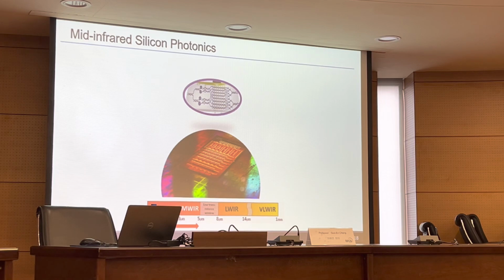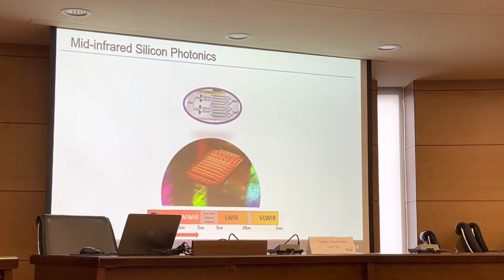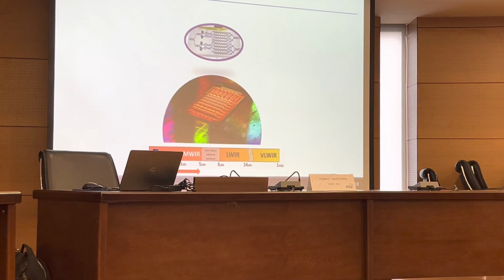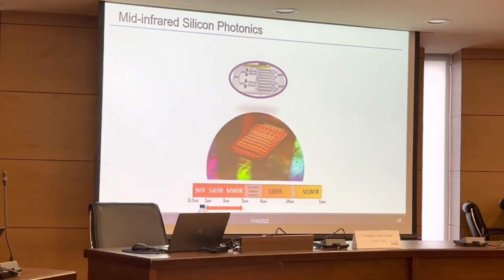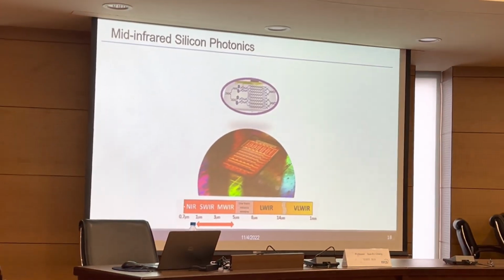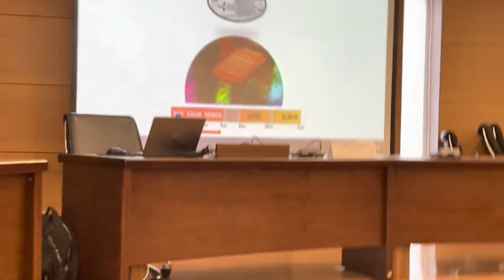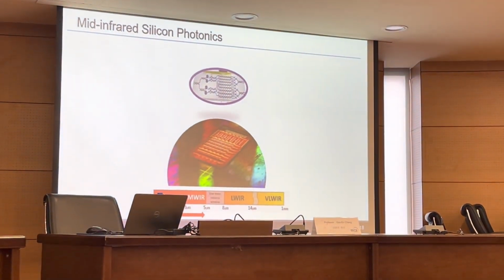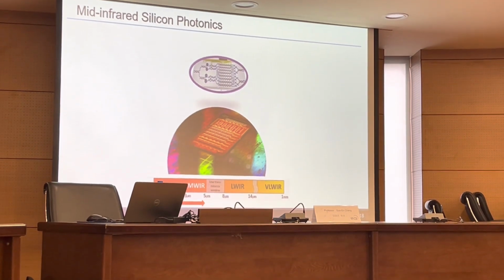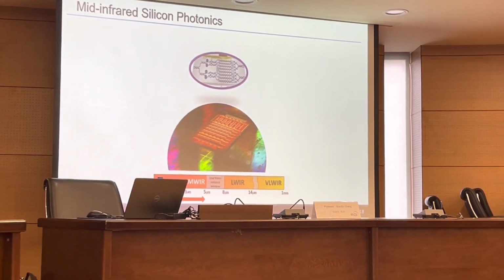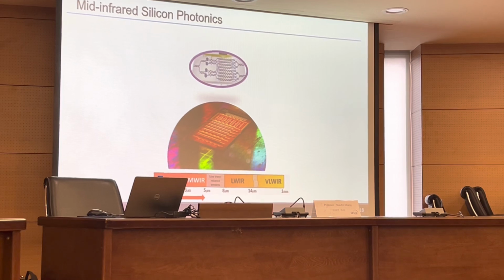So for the operation range of silicon germanium tin devices, we are trying to push the range from near infrared to mid IR. For conventional silicon germanium based photonic devices, the operation range is mostly in the near IR, from about 0.7 micron to about 1.4 micron.